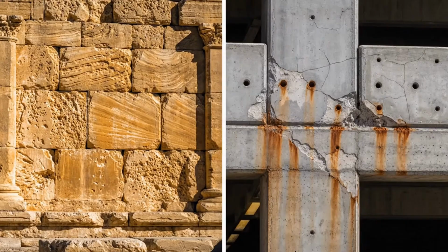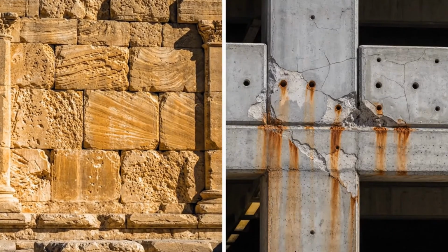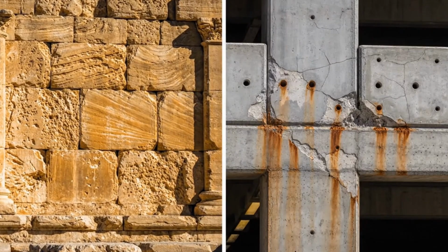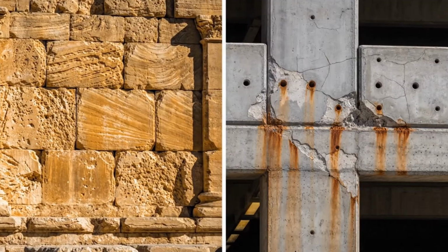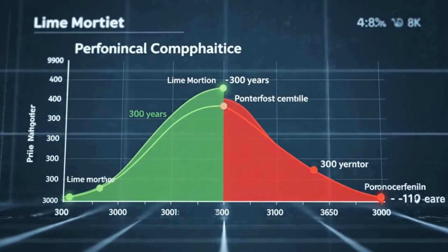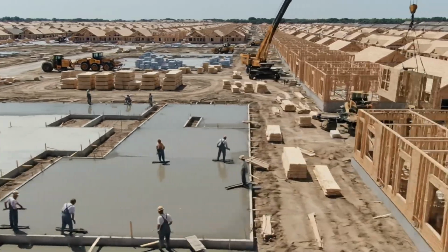The joint does not remain a weak boundary. It becomes continuous stone, and when microcracks form, the carbonation process heals them. Carbon dioxide and moisture penetrate the crack, react with exposed calcium hydroxide, and deposit fresh calcium carbonate that seals it from inside. This is autogenous healing, documented in samples from Roman construction to Crusader fortifications to the Temple Mount itself. The mortar heals itself, chemically, measurably, continuously.